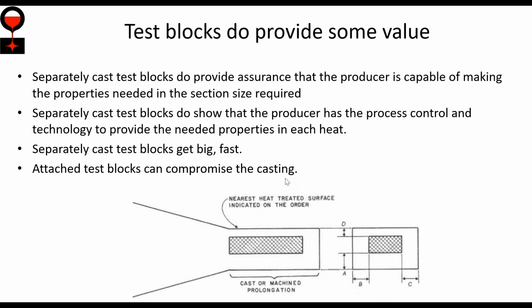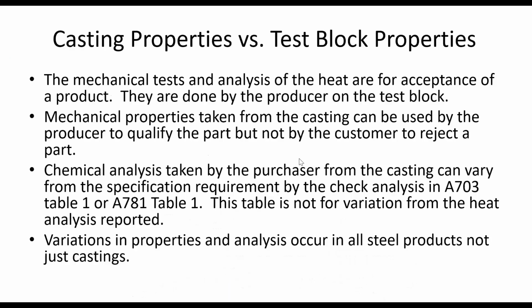One of the other things that people will often do is say, I'll just add a chunk on to the casting and then I'll cut it off and get the tensile test from that chunk. And that can be a good and useful technique. But if you do this, and I'm worried about this section here, then what I'm really doing is making a test block that shows me what the properties would have been here if I had not put the test block on. But putting the test block on means I'm going to have poor material out in this area right where I want good material. So generally, adding a block on needs to be done carefully, or you compromise the material in the casting where the test block is attached.